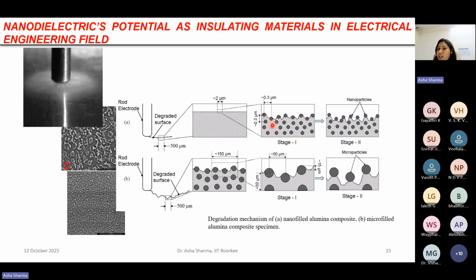Here as well, there is no degradation of the material. Here as well, there is no degradation of material. The only part that is degraded is the material in between these two. It means if there was no nanoparticle, the whole thing would be eroded very easily, very early. But if the nanoparticles are present, they provide a hindrance to the degradation and erosion, right? So again, this is good for my power system. The failure will be less because of this material enhancement.